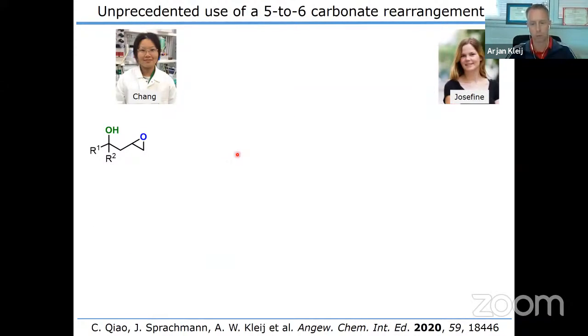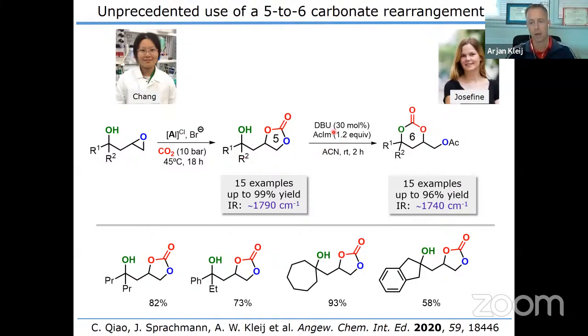The second step is a little bit more complex, but what we do, we use basically DBU again and acetylimidazole, and we get here a 6-membered cyclic carbonate being exclusively formed. Well, the way this works is as follows. The 5-membered cyclic carbonate is in equilibrium with a 6-membered cyclic carbonate. However, when you take the NMR of this 5-membered cyclic carbonate, you don't see this 6-membered cyclic carbonate being populated in your NMR tube. And that's because the equilibrium is almost on the side of the 5-membered cyclic carbonate, which is the thermodynamically more stable compound.